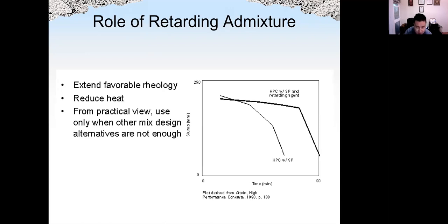Here shows the role of retarder. So this is the time. We have high strength, high performance concrete with superplasticizer, and with superplasticizer and retarding agent. We can see with retarding agent, it will extend the rheology. We have longer time for higher slump, so the slump loss is smaller. So we have more time to work on concrete. It will also reduce the amount of heat, reduce the temperature.